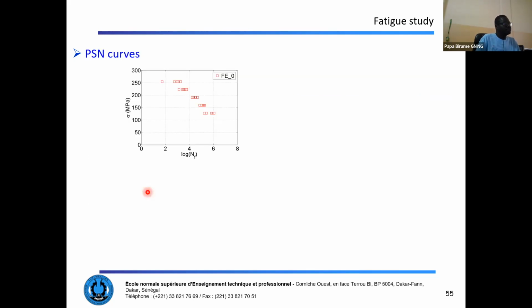So the test shows clouds of points, and the test was stopped at 2 million cycles. The higher points correspond to 80% of the ultimate tensile strength. The lower correspond to 40% of the ultimate tensile strength. So once these points, these life cycles were obtained depending on the loading stress,